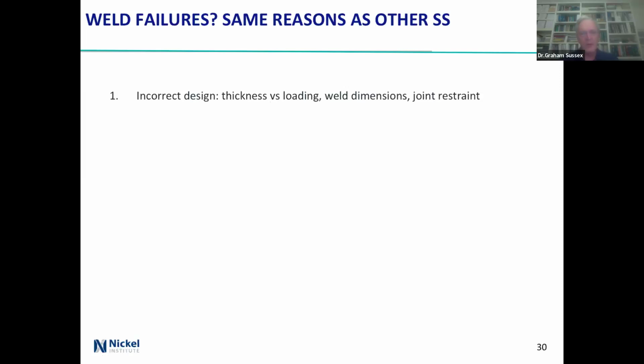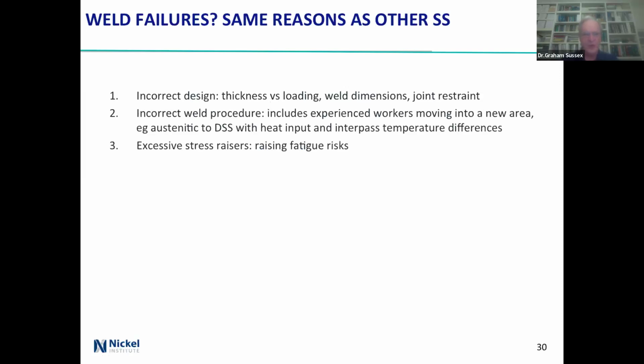Okay, why do you get weld failures? Well, incorrect design, thickness versus loading, weld dimensions, joint restraint, wrong weld procedures. They're experienced people working into a new area. So somebody who's used to welding austenites and moves across to duplex, heat input, interpass temperature differences, because interpass temperatures for the austenites tend to be not nearly as sensitive.